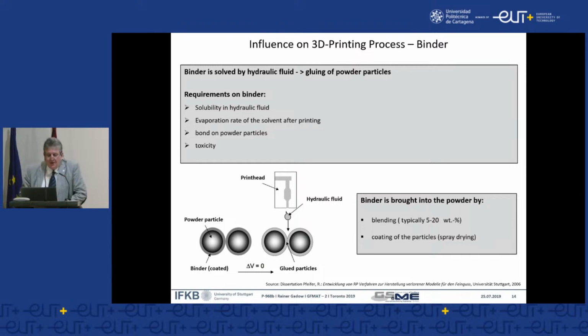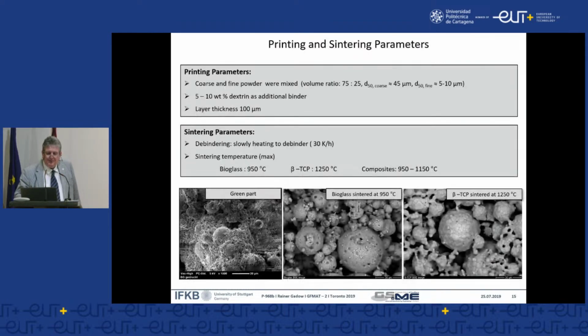So the binder is brought into the powder by blending, that is one solution, and the second one is by coating of the powder. And that was another research field in our institute, the coating of ceramic powders, for example, to create very complex zirconia materials. And if one has this know-how, it is easy to adapt it for such other purposes.